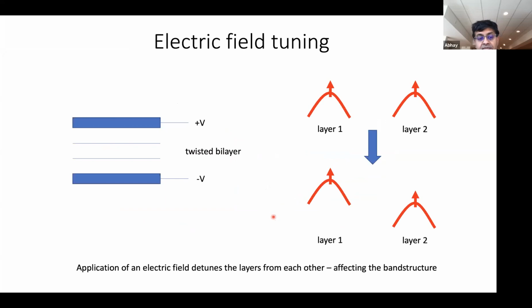Okay, so something very nice about this particular system is that you can use this electric field degree of tuning to actually tune the band structure. So here is sort of a cartoon picture of how that happens. As I apply this electric field, initially I have electrons that are present in both the layers, and both of these at the top of the valence band are degenerate. But once I start to apply this electric field, then there's an on-site potential energy difference between electrons in one layer versus the other layer. And so you can see that this is a nice way of tuning the actual band structure.